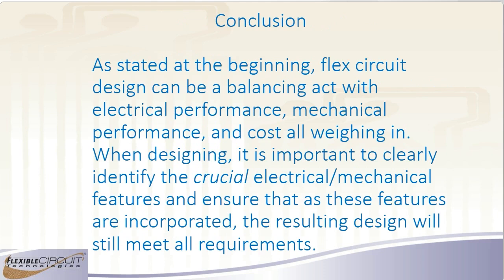So anyway, just to conclude, when you're designing your flex circuits, it really comes down to a balancing act. And too many times, a design is driven too much by one particular feature, electrical features, for instance, and you can have a circuit that is absolutely flawless electrically, where you have the most pure signals going through it, but if you form it and put it in your device and it breaks in half, it doesn't really do you any good. So you have to have a balancing act, and usually it's a little bit of give and take, where you may not get the 100 ohm impedance that you wanted, but maybe 90 is good enough, because that will allow you to bend it and actually get it to function mechanically also.